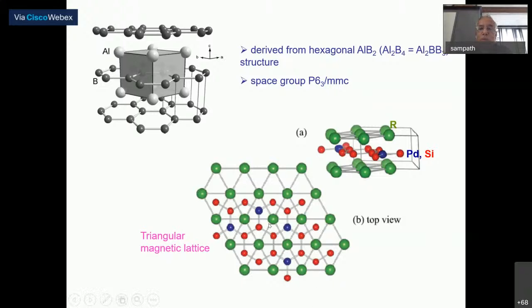I'm showing this example of palladium silicon, R2PdSi3, the rare earth compound's crystal structure along the C-axis. This is the hexagon which I already mentioned here. These are all silicon here, and you have the palladium here. And then this palladium silicon layer, as I already mentioned, is sandwiched by the rare earth layer here. This is along the C-axis. This is shown in another form here. This is the palladium silicon layer. Blue is palladium, red is silicon, and green is rare earth here. You can see these layers alternate here. We basically have a triangular lattice here. Therefore, there is enough scope for magnetic frustration, geometrically frustrated magnetism.